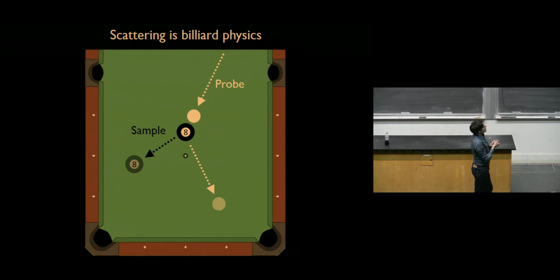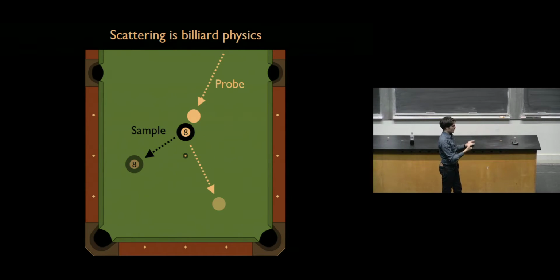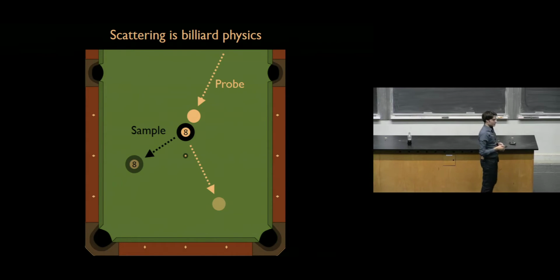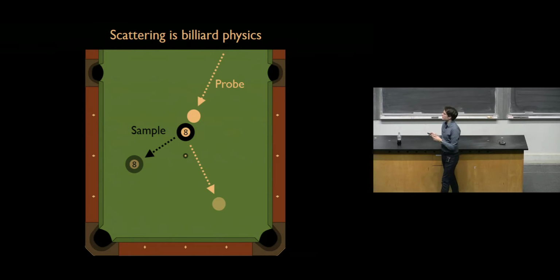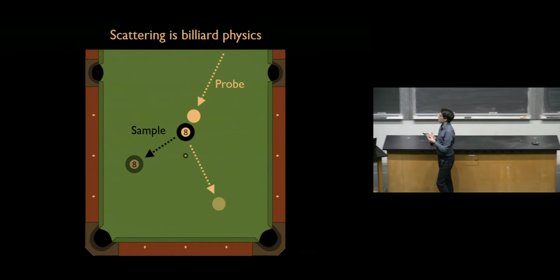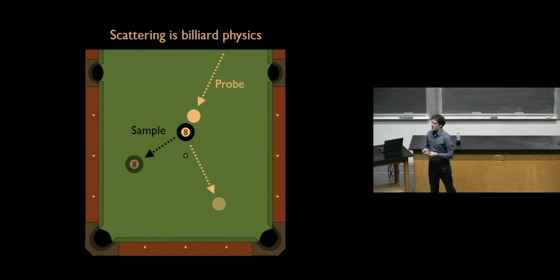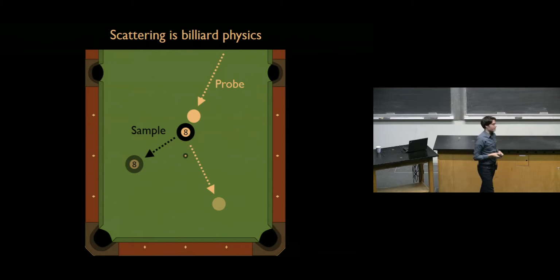So the bottom line is that once we've transferred this momentum to the sample, there's no way we can measure the momentum of the sample directly, because this is a massive object. It's not like we can put it on a scale or on a dynamometer and measure how much momentum we've given to it. So what we end up doing is we use a probe that has much smaller momentum than the sample has, and we look at what happens to the probe when the probe scatters from your sample.